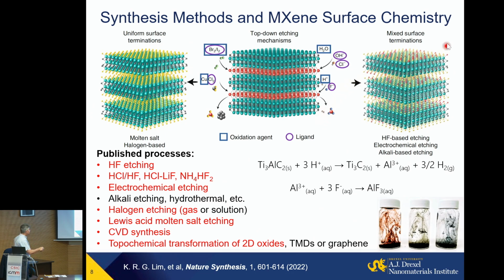But again, keep in mind, depending on the surface chemistry, even for nominally the same, say, titanium carbide Ti3C2 MXene, you will get different properties. For example, these materials produced by wet chemical etching will be easily dispersible in water because they will be hydrophilic, forming stable colloidal solutions. And you see different MXenes will give you different colors because of different optical and electronic properties. But halogen terminated MXenes will be hydrophobic. So again, you can control properties through synthesis of materials.